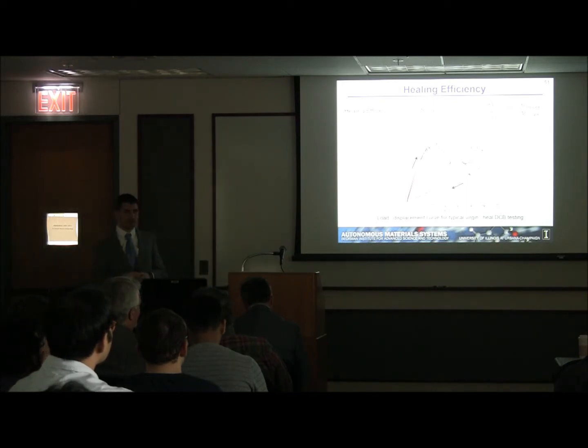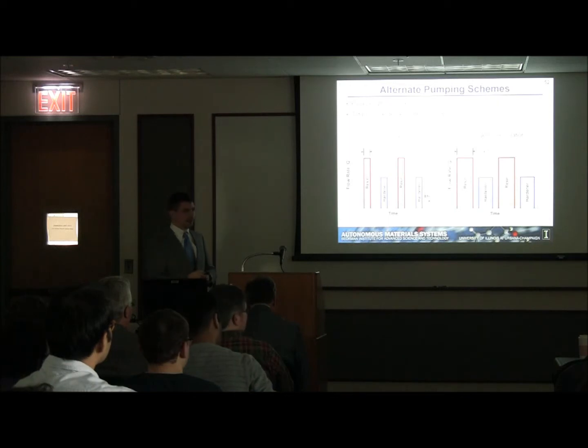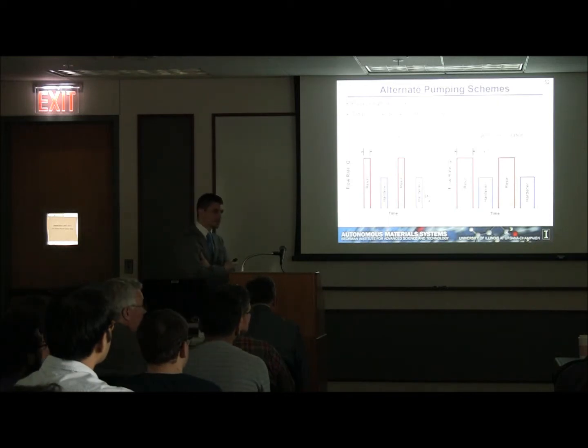In our particular case, since we have the same sample, which has the same width B, and the same crack advance length delta A, that simplifies to the ratio of the energies required to open the cracks, delta U, or the ratio of the encompassed low displacement curves here. So in this particular sample, we had a healing efficiency of 105%. So that tells us that we recovered 105% of the original fracture toughness of the material using our particular delivery scheme. What is the crack opening of